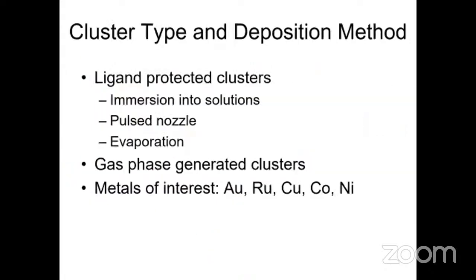As I mentioned before, we need this cluster to be deposited on the metal oxide, with the ligand. We either immerse it in the solution, or use a pulsed nozzle, or evaporation; we're trying different deposition methods with different criteria. And we generate them with different metals. But I will just focus on gold 9 in this presentation because this is the core of my research.